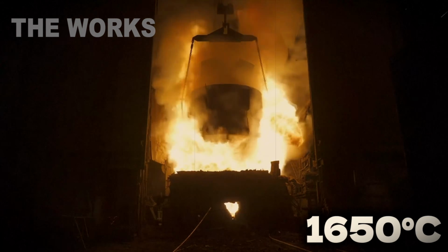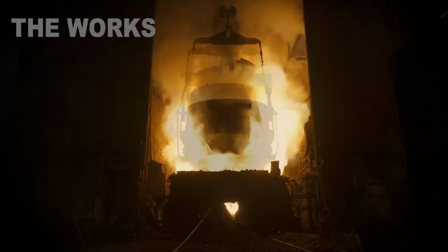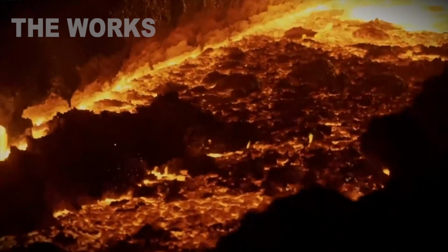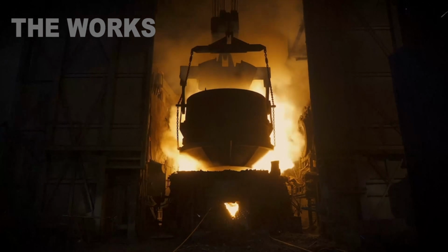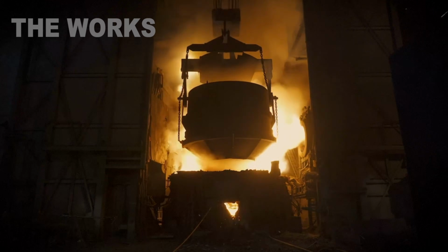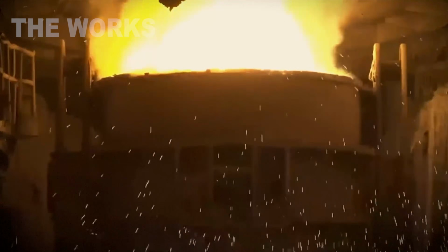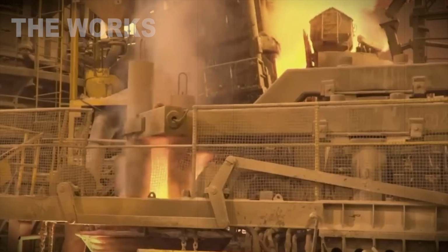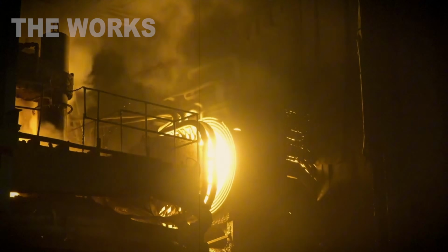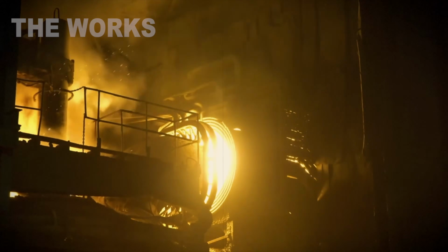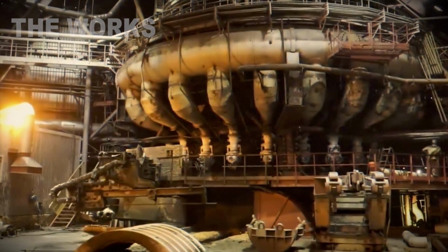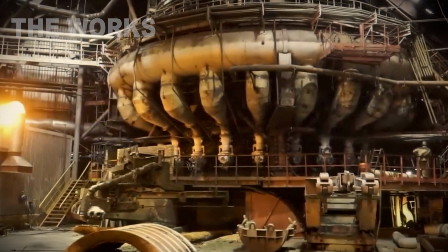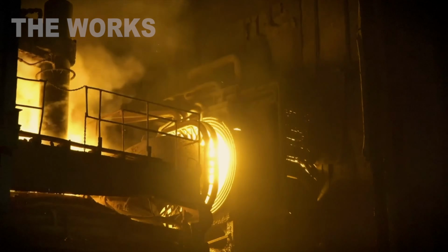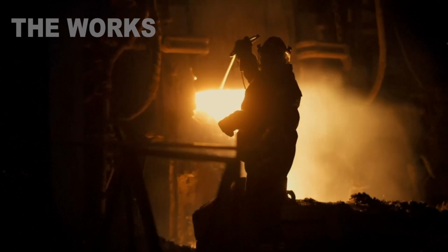Melting time, 3 hours. Lab techs pull samples every 30 minutes. Analyze composition on a spectrometer. Adjust with ferroalloy additives. Precision matters. Carbon tolerance, plus or minus 0.05%. Nickel, plus or minus 0.1%. Finished melt pours into a ladle. The ladle weighs 200 tons. From the ladle, it flows into molds.